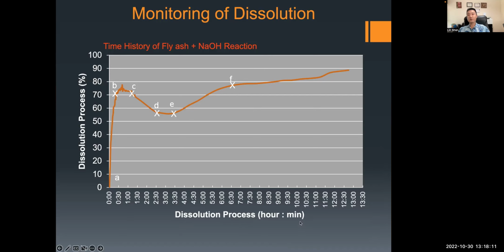So this curve kind of reminded me of the classic hydration process of C3S. Here we can see a competing effect of dissolution and gelation, which is the formation of geopolymer. So in the first phase, A to B, we see the dissolution process increase, which means the concentration of ions increases over time. So the precursor is dissolved by sodium hydroxide. Then it achieves its saturation point, and then the concentration goes down. That means we have hydration product, we have geopolymer formed. However, in this case, we have some excess sodium hydroxide which further dissolves the geopolymer. So the concentration of ions actually increases again.